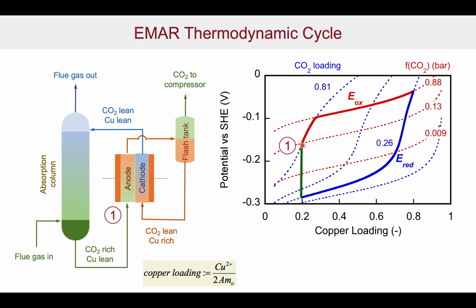And we then begin to start passing current through the system. Copper gets released. CO2 then gets kicked off from the amines, and the concentration of free CO2, dissolved CO2, increases in here, just as pure CO2, carbonic acid. At some point, we get to a saturation level, and once we're at saturation at that particular pressure, fugacity, any additional CO2 released will come off as a gas, and we maintain a constant pressure, or constant fugacity, in the system.